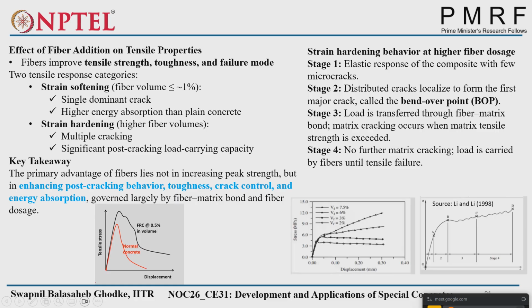This strain hardening behavior plot is divided into four stages: stage 1, stage 2, stage 3, and stage 4. Stage 1 shows the elastic response of the composite with a few micro cracks. This one. Stage 2, distributed cracks localize to form the first major crack. Here you will observe the first major crack at point B. Then load is transferred through the fiber-matrix bond. Matrix cracking occurs when matrix tensile strength is exceeded. This means the first crack appears.